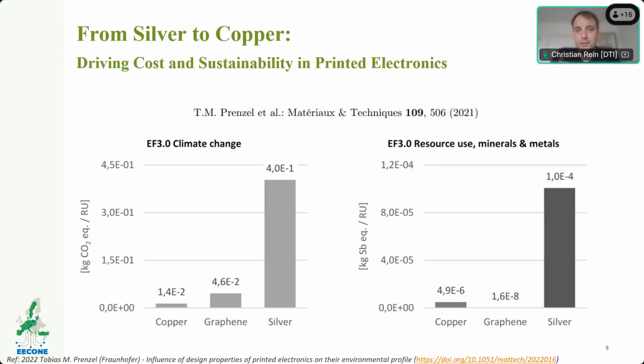And one of the questions that can sometimes be met when you are suggesting a new material to include is, well, why didn't the status quo work? Right now, a lot of silver is being used in printed electronics, since it was a standard that's been used, silver flakes. But one of the things that needs to be taken into account is the very high climate change potential, and the overall environmental impact that using silver has in comparison with copper. Shifting from silver to copper reduces the overall environmental footprint by 96.5%. Thus, there's a very large driving force to move into the copper particle regime instead.